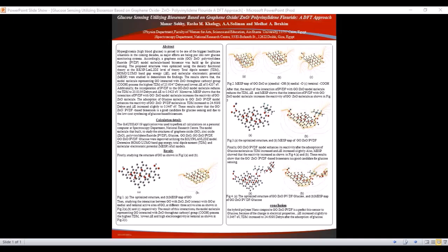Finally, the absorption of the glucose molecule to graphene oxide zinc oxide polyvinylidene fluoride model enhances the reactivity of the graphene oxide zinc oxide polyvinylidene fluoride molecule as total dipole moment increases and HOMO-LUMO band gap energy increases slightly. This result shows that the graphene oxide zinc oxide polyvinylidene fluoride based biosensor is a good candidate for glucose sensing.